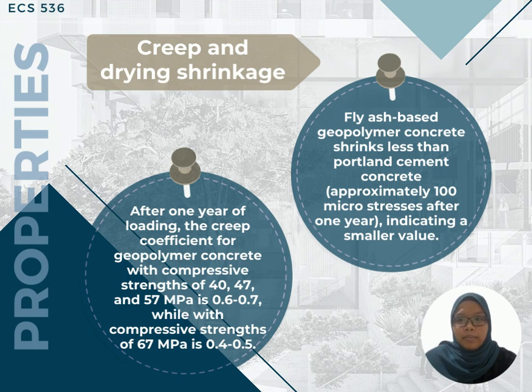And lastly, creep and drying shrinkage. Fly ash based geopolymer concrete undergoes very little drying shrinkage, about 100 microstrain after 1 year, compared to 500 to 800 microstrain experienced by Portland cement concrete, indicating a significantly smaller value. The creep coefficient after 1 year of loading for geopolymer concrete with compressive strength of 40, 47 and 57 megapascal is between 0.6 and 0.7, while for geopolymer concrete with compressive strength of 67 megapascal, this value is between 0.4 and 0.5.